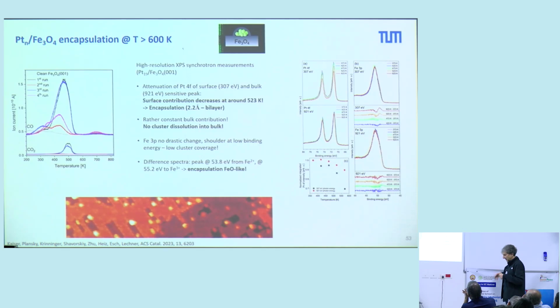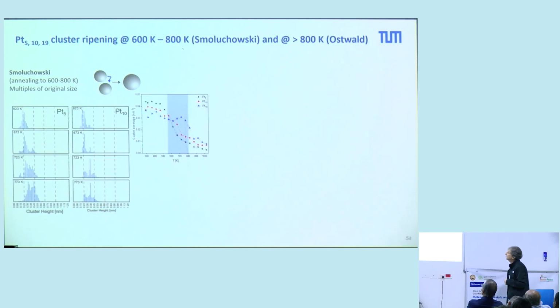That means we have now in the next step this encapsulation. And now let's have a look at what happens later. We heat up again. Remember, these clusters are now encapsulated with an iron oxide film. And then if you heat further up, you see that you change the density of the clusters. You have ripening. That means if you change the density, it means that they migrate on the surface, they coalesce, you have Smoluchowski ripening, you have larger clusters, and you decrease the cluster density.